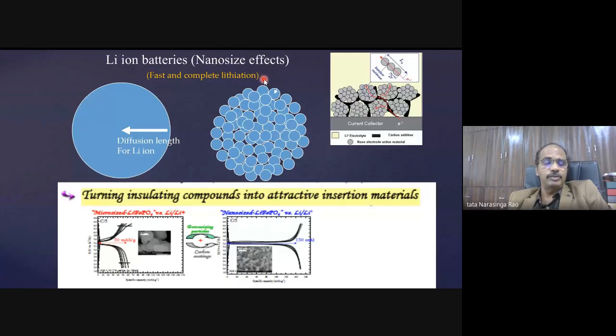So the charge and discharge is very fast, and all your material gets lithiated in a short time, whereas here it takes a long time. So if your battery has to be charged for a given time, you can see here, it gets only 50 milliampere hour if the size is 1 to 2 micron lithium iron phosphate particles. If you have nanoparticles, here you have 150, 3 times more, because it quickly gets lithiated, or when you discharge, it gets delithiated. So the size effect is more important.